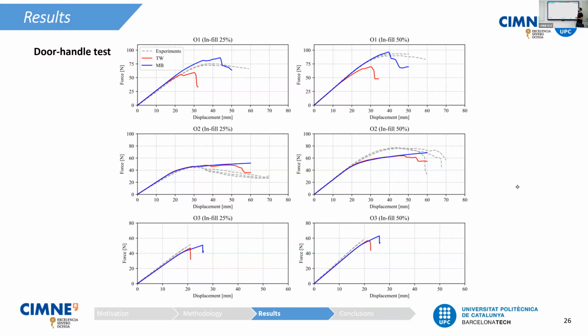If we now take a look at the damage criterion, we get the same conclusions, meaning that for the first orientation, orientation 1, we can see that the blue line corresponding to the mechanism-based damage criterion fits the experimental results a lot better than the red line corresponding to the Tsai-Wu criterion. While for orientation 2 and orientation 3, similar results are achieved with both criteria.